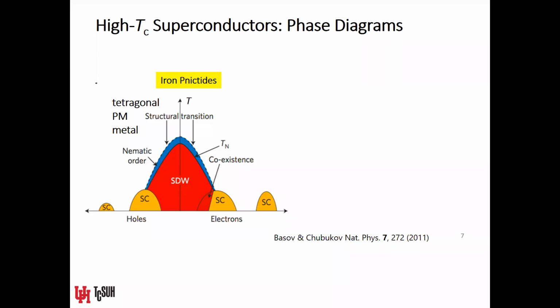Now this particular phase diagram is showing both hole and electron doping. And the diagram is meant to point out the evolution of the structure and the magnetism in the material as the iron pnictide is driven into the superconducting phase. So at high temperatures in the normal state, most of the iron-based superconductors are tetragonal. They are paramagnetic, so they have no magnetic ordering, and they are somewhat weak metals. So in the normal state, they're typically in a weakly metallic state.